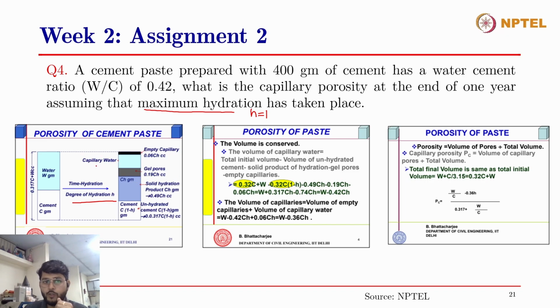The volume of capillary water can be found by this expression: total initial volume minus the volume of unhydrated cement minus the solid product of hydration minus the gel pores minus the empty capillaries, and that will give you W minus 0.42 H. Now, the total volume of capillaries will be the volume of empty capillaries plus the volume of capillary water. And we know that the volume of empty capillaries is 0.06 H. So the volume of capillary water is W minus 0.42 H.